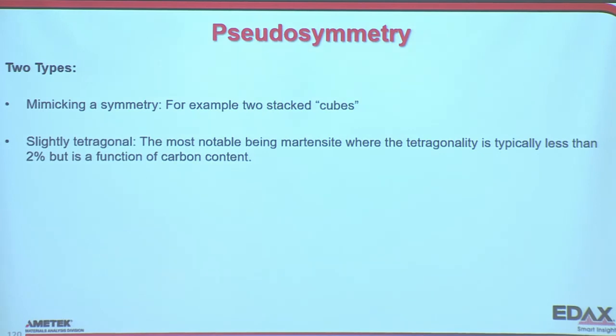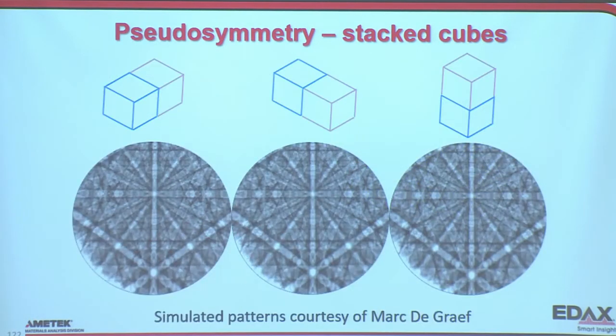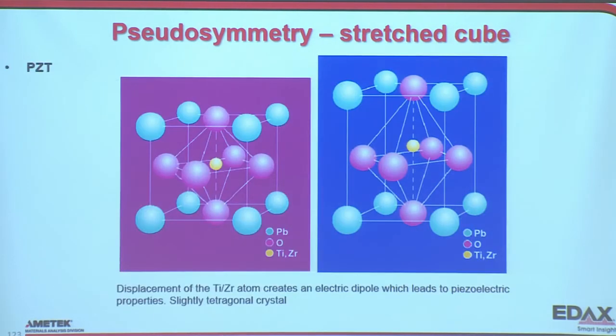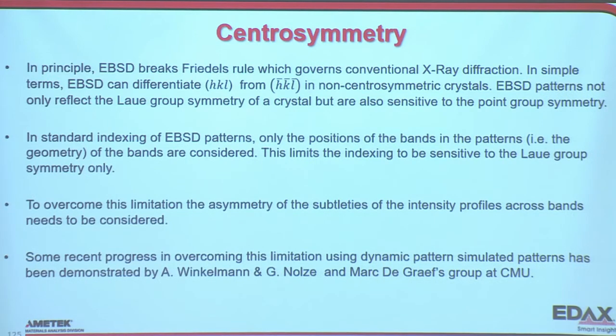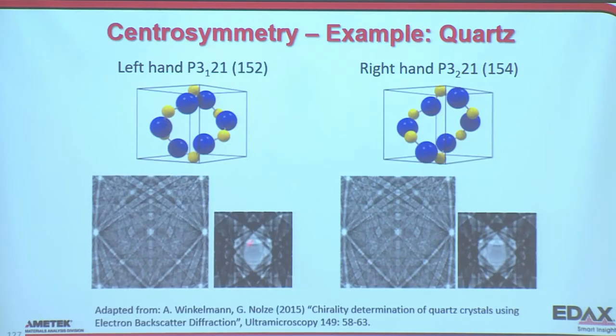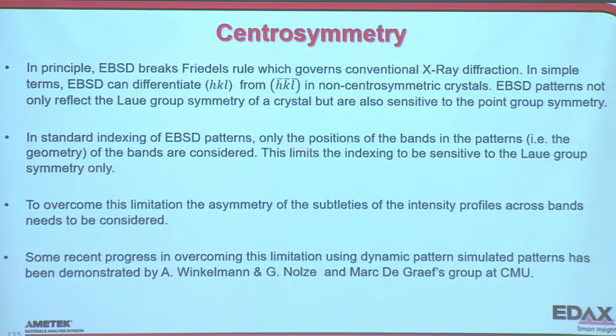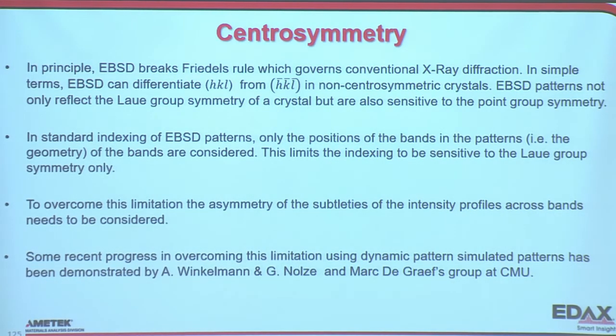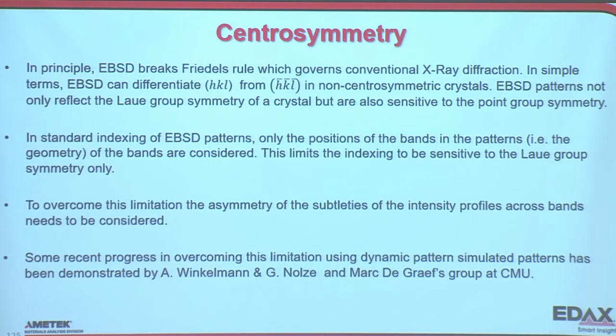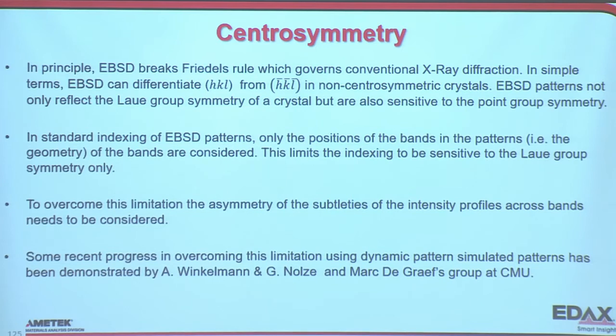I wanted to mention pseudosymmetry in particular. I mentioned this pseudosymmetry problem and how difficult it is to distinguish these patterns from each other. And this example, and then this one. So I mentioned the centrosymmetry one, and this is the one I wanted to bring up. So, like I said, these are simulated patterns, and we can look now. We know it's the intensities that make a difference. So if you think about the Hough transform, we only care about the positions of the bands, the geometry. And so we can't see these subtleties in the intensity profiles in the bands. We actually ignore the intensity. The Hough transform finds the bands, and it's really good at locating this one here in the pattern, this one here in the pattern, but it doesn't know anything about the subtleties of intensity.